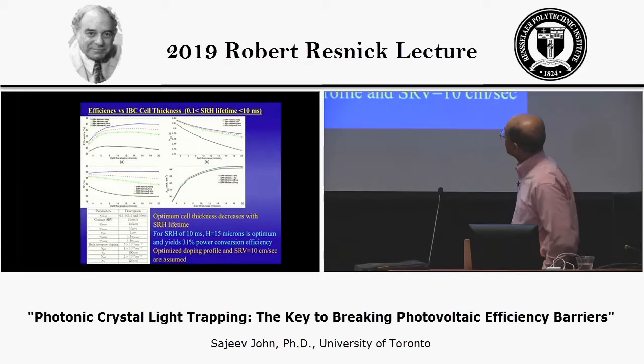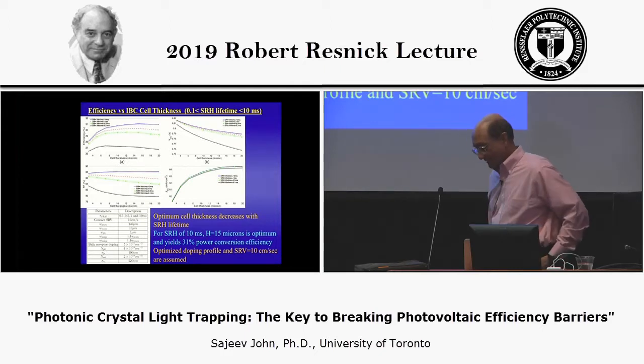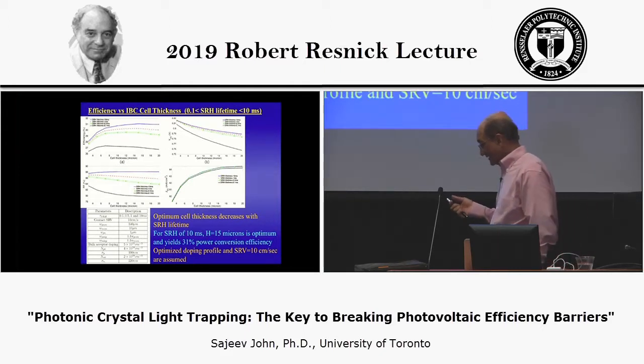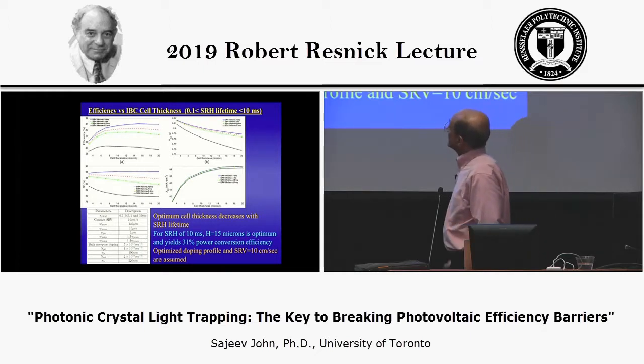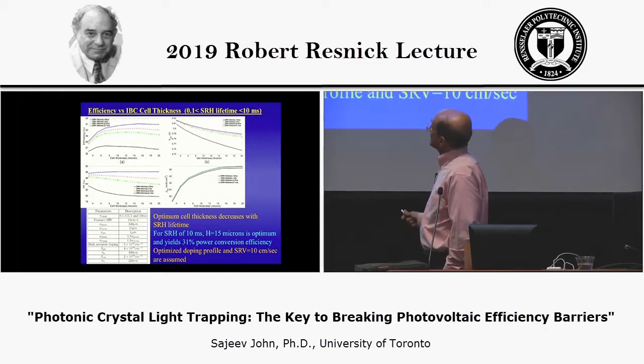So it's these sort of structures that we can now consider in terms of the semiconductor drift diffusion equations. And here I plot an interesting result as a function of the cell thickness, assuming an optimized inverted pyramid architecture on the top and back contacts only, what the efficiency would be as a function of that thickness.